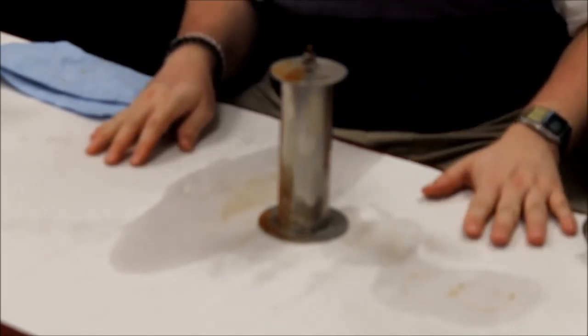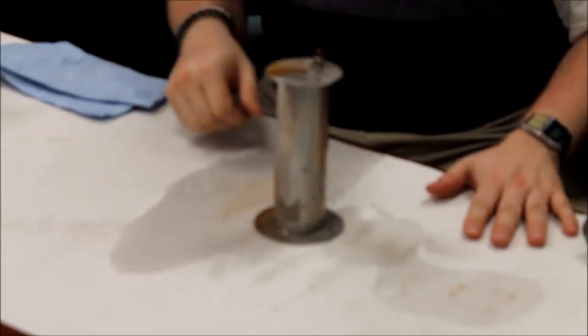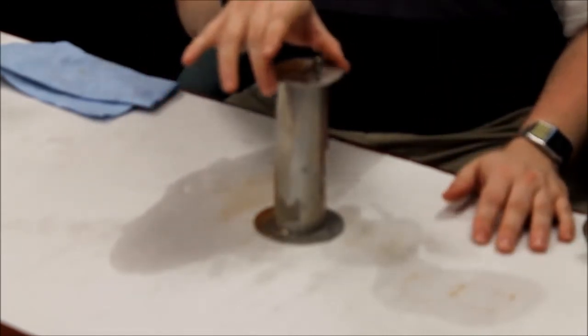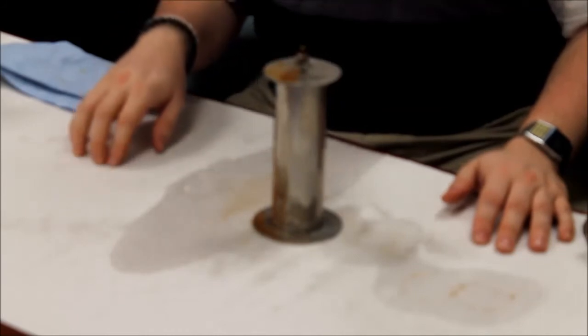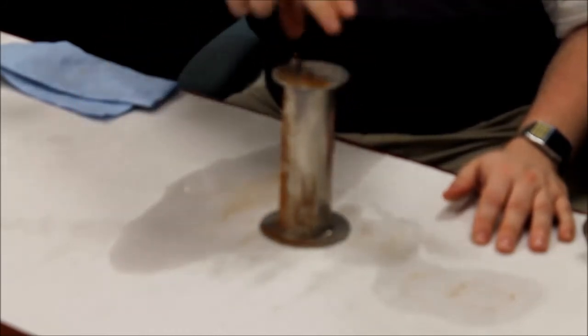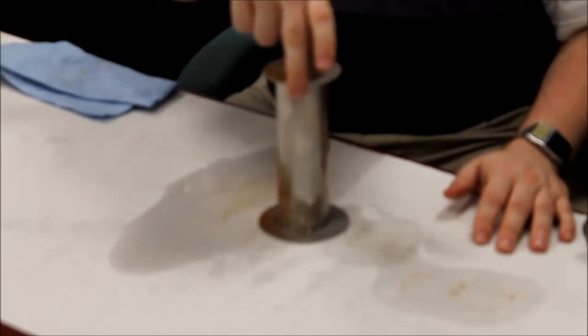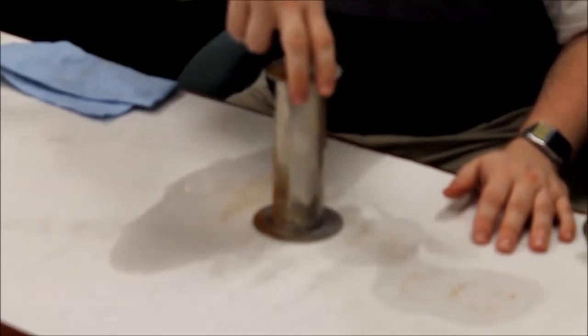Here's an example of the extra protection that Rust Rescue can provide in a high chloride corrosive environment. This was cleaned up with the CitriSurf 2310, and then this half treated with the Rust Rescue, and then exposed to a corrosive environment for 6 months. And you can see the difference between the treated and untreated sides there. Now, it's not a coating or a sealer for the entire surface like a lacquer or something like that would be. It's just protecting your surface from the effects of the pitting.